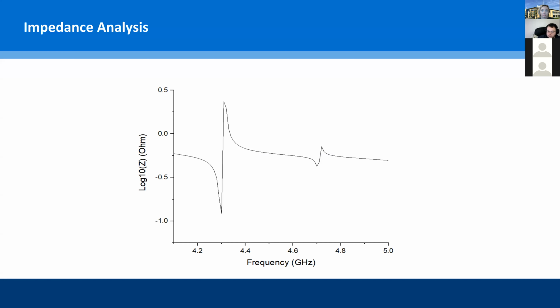If the second mode, which we get at around 4.7 gigahertz, is by the zinc oxide layer with the silicon dioxide layer, and it is a dual mode, then it could be used for temperature measurement along with the mass measurement system. So the results we were happy about were that we were able to get higher resonating frequencies than the existing design, and we were also able to get a dual mode to some extent.